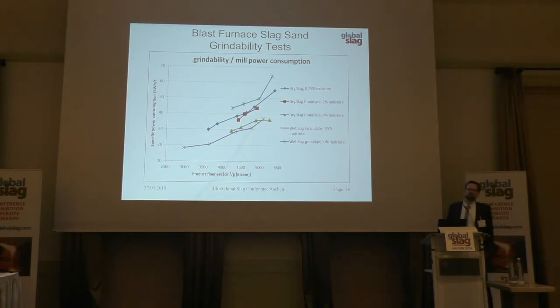The first thing you would do with the granulated slag is grind it up. Therefore, the company Loesche has done grinding tests. We compared the dry granulated product with the wet granulated product in the grinding test. As you know, the grinding efficiency increases with higher moisture content, and normally with wet granulated slag, depending on the storage and on the dehydration of the product, you still have a lot of moisture, up to 10%, in the slag. On the other side, our dry granulated product has nearly 0% moisture. So for the grinding test, we also added some water to the dry granulated product, and we also dried the wet granulate to have a good comparison of these two products.